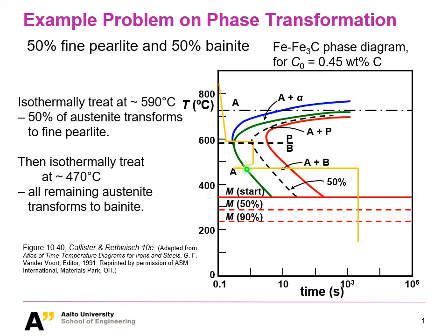So starting from this time, your 50% of austenite will start to do the transformation. But now you need to only consider your austenite, right? You can treat your austenite as 100%, and it will start transformation. So when it reaches this point, you have basically bainite transformation, 50% of bainite and 100% of bainite, and you just hold it further. Make sure you completely cover the time that you converted back. You have to cover this time back by a certain amount, and even with a little bit of safety margin, you make sure at the end you have full transformation to bainite.